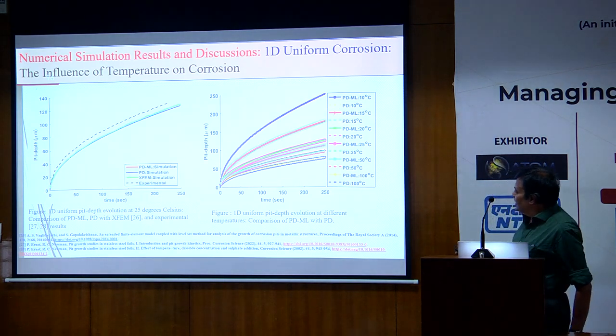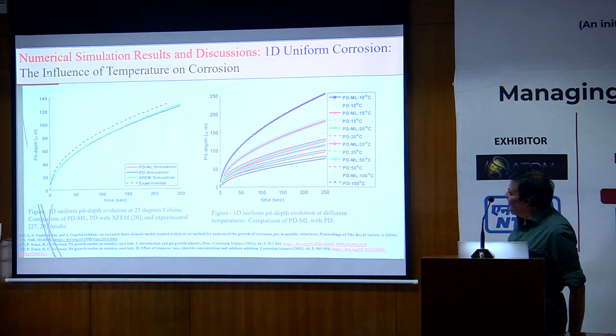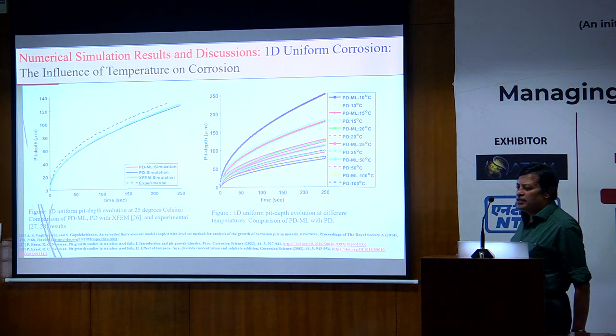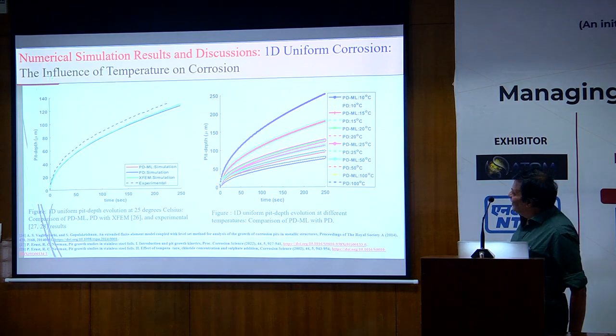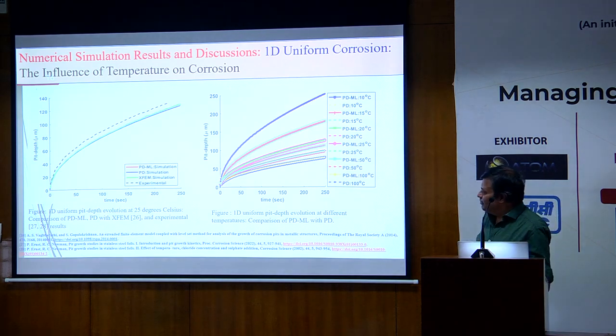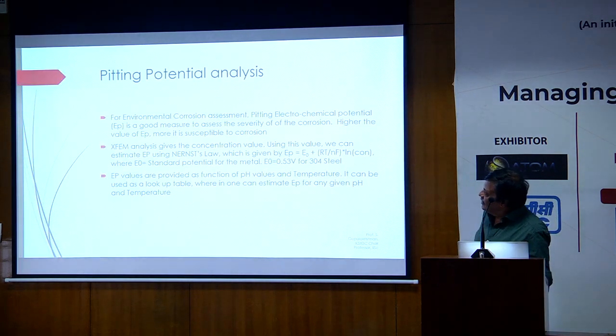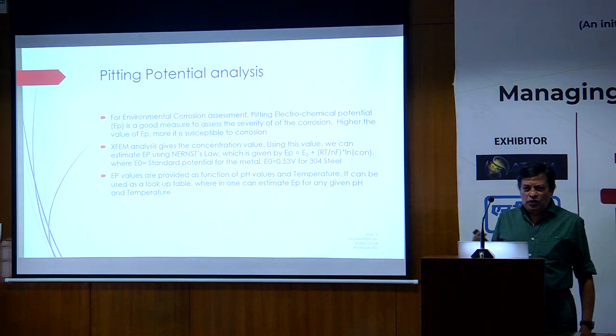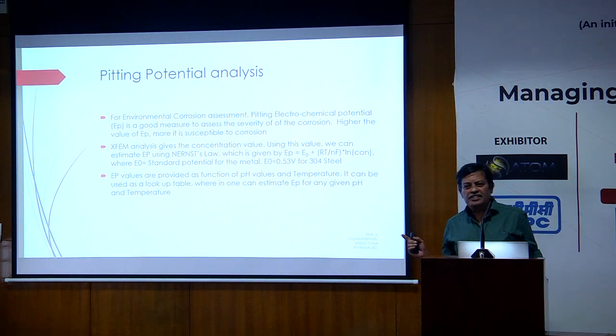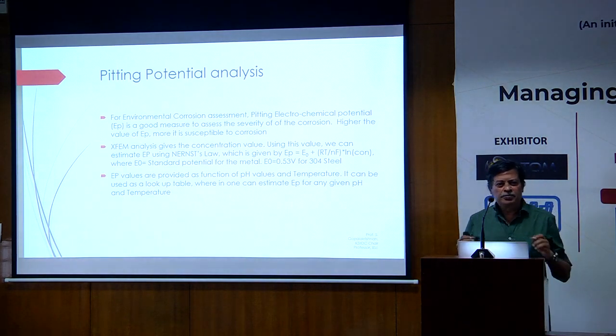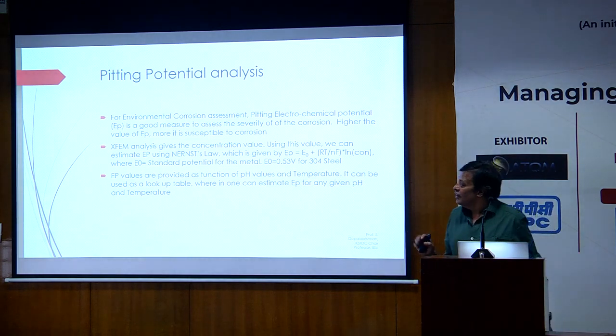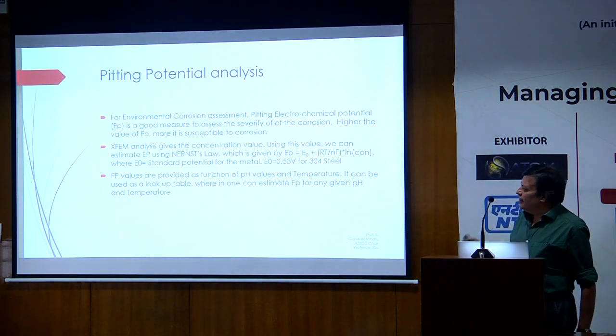And the right-hand side is basically the pit profile as a function of different temperatures. And we got it both from the peridynamic solution and from peridynamics and machine learning solutions. In this second analysis, we didn't put any stress. It is purely environmental corrosion. So we can do some more analysis.